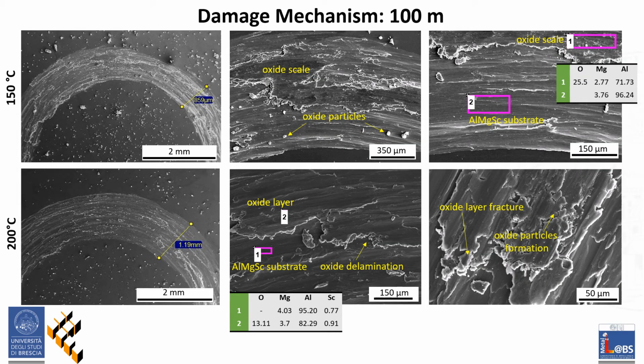In these cases, oxide delamination and fracture with particles formation can be detected, together with the underlying Scalmalloy substrate in the areas where the oxide has already been removed, as for example in the images above on the right and in the central one below.